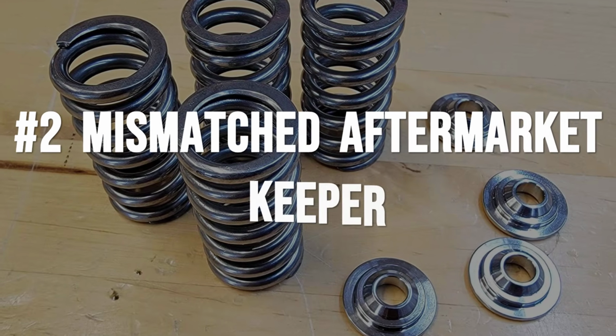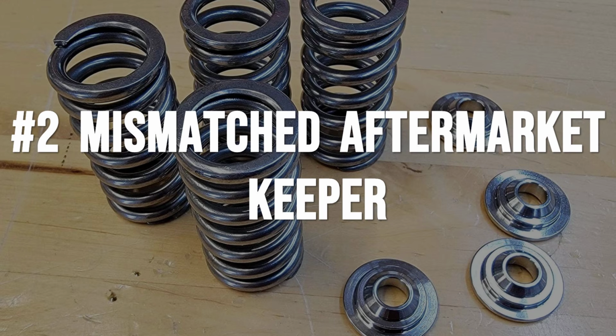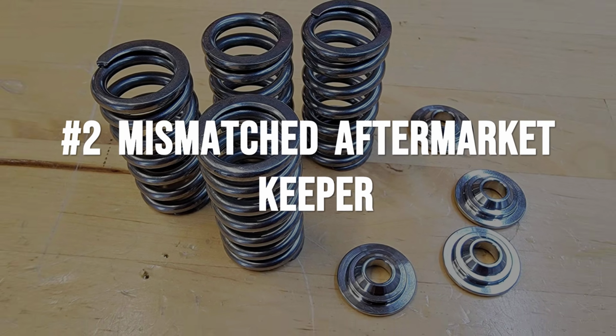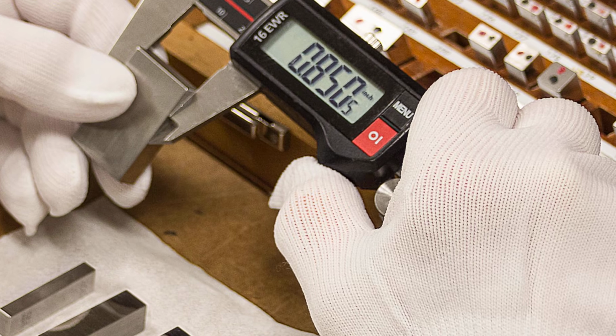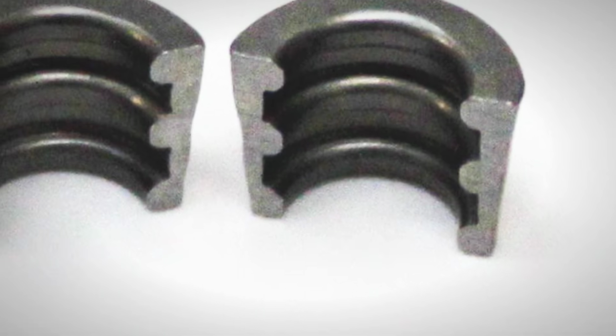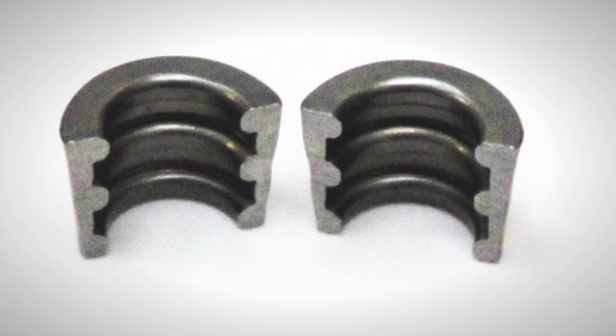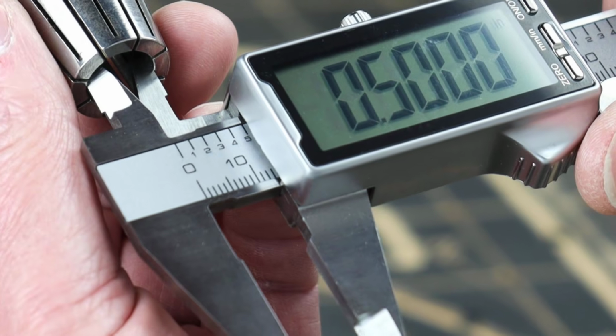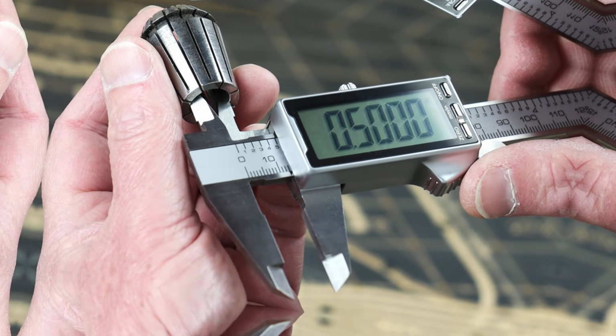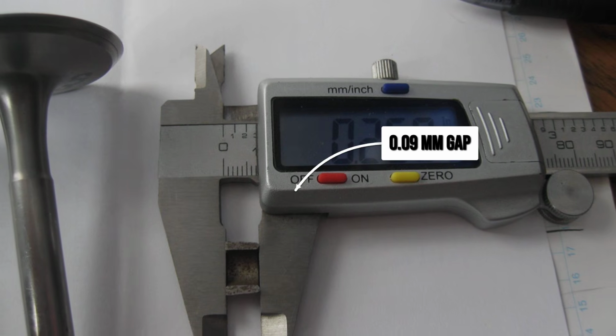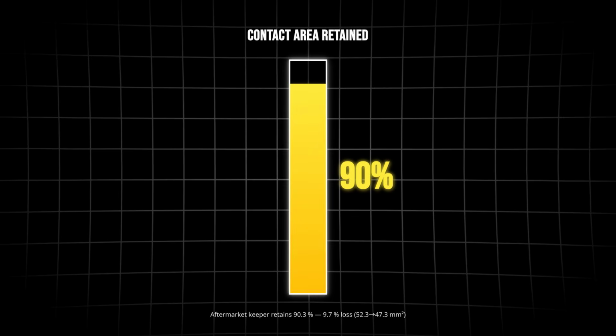The mismatched aftermarket keeper is a crime of decimal points and corporate indifference. The dimensional inspection report is explicit. The keeper radius is 1.91 millimeters. The OEM specification is 2.00 millimeters plus or minus 0.02. That gap, 0.09 of a millimeter, cuts the contact area by nearly 10%.